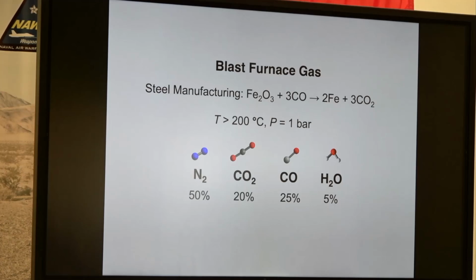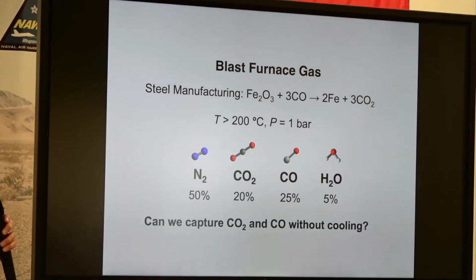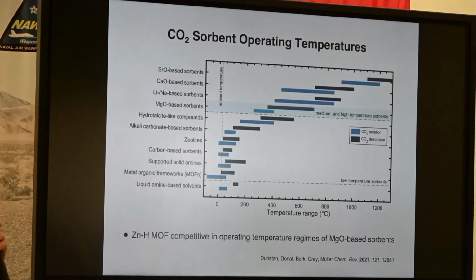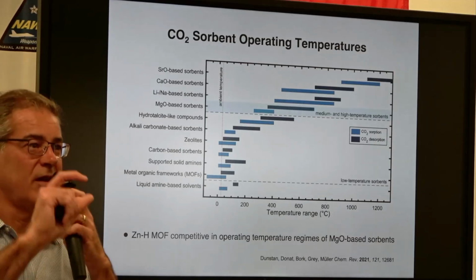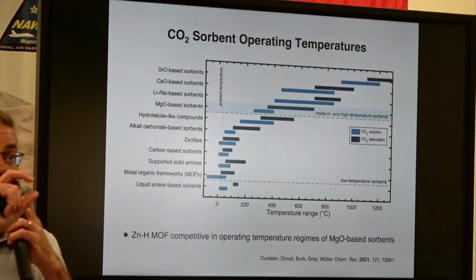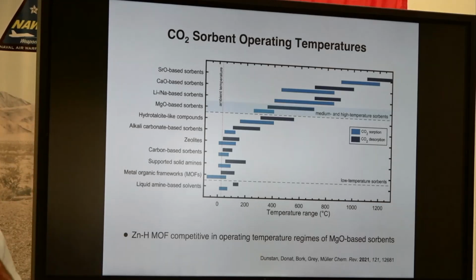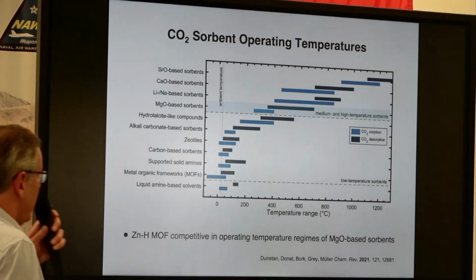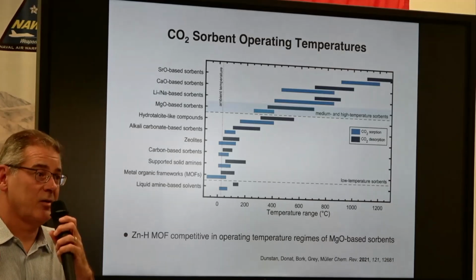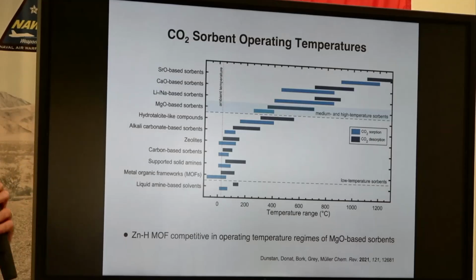So how could we do that without cooling? If we can do it hot, we can even feed hot CO back into the reactor. So can we capture CO2 and CO at these high temperatures? If you look at porous solids, there's nothing that CO2 sticks to at 200 plus degrees, right? If you want to grab CO2 chemically, you're going to need a reactive oxide, a metal oxide. This is a dense compound. Those oxide anions will react with CO2 to make a carbonate. And that works, but it's very slow because you make a layer and more CO2 can't penetrate. And also, when you desorb CO2, you have to go to extremely high temperatures to get an appreciable rate of loss of CO2. There's no porous solids in this window of 200 to 300 degrees C.